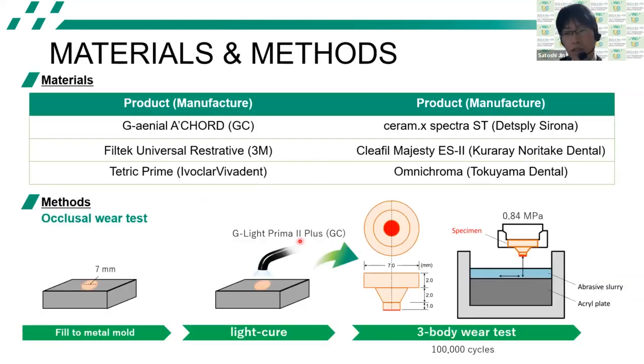The materials and the occlusal wear test method are shown in this slide. Materials shown in this table were filled in a mold and cured to prepare specimens of such shape. While applying a load, collision and slide motion were repeated against an acrylic plate. The length of the specimen before and after this test was measured, and the amount of wear was calculated.